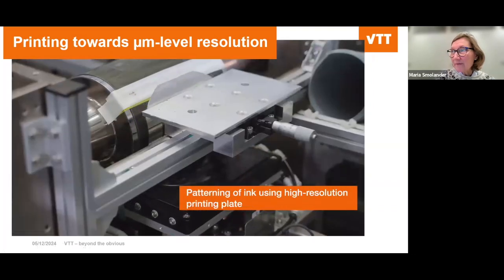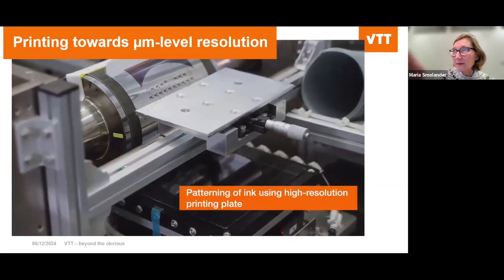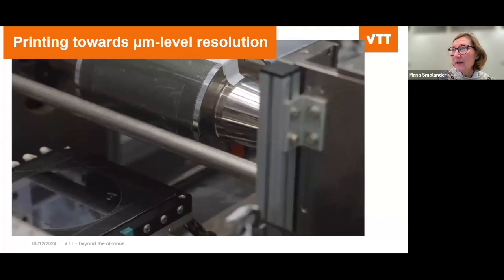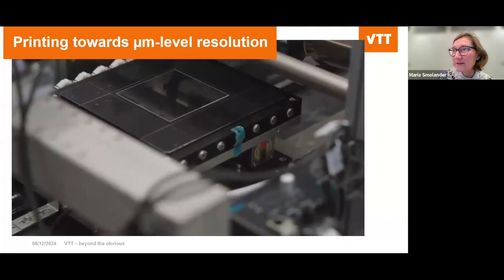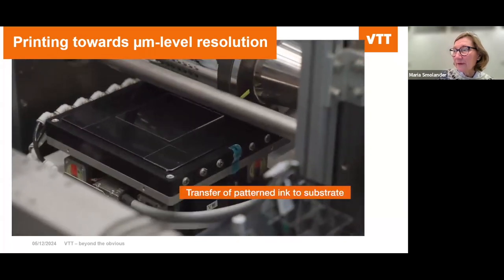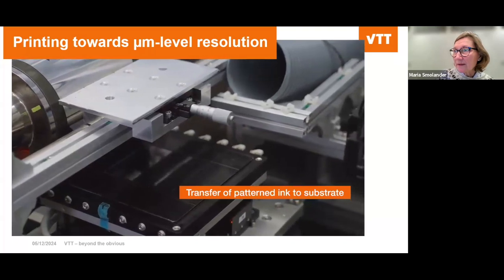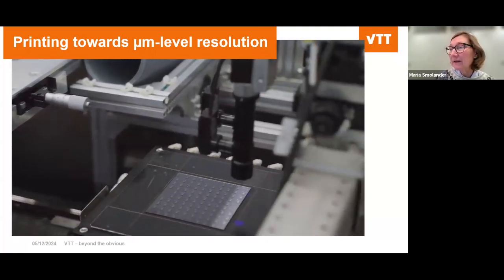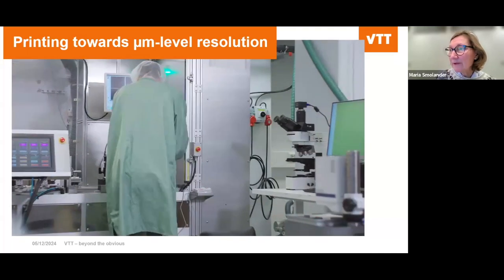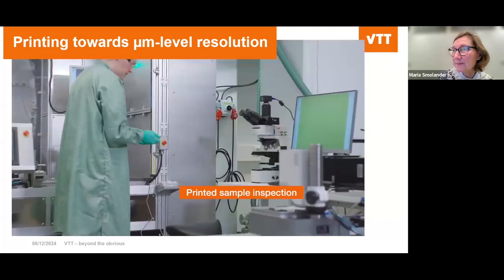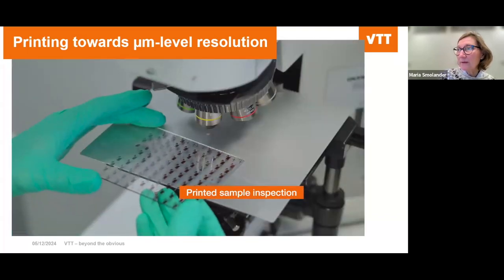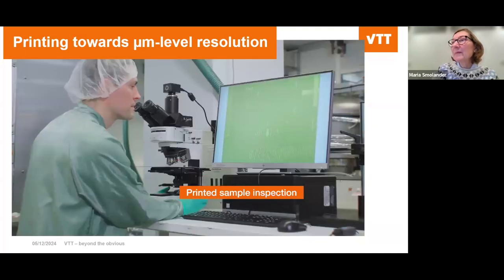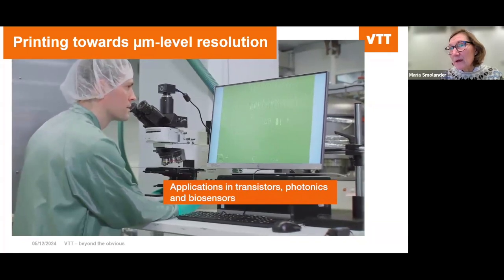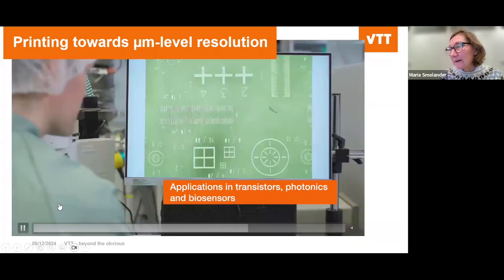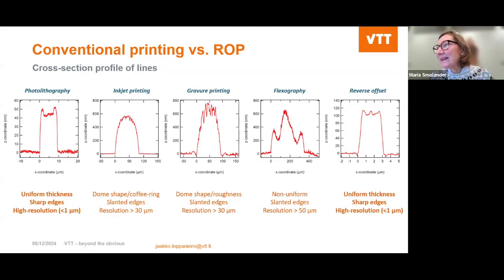And now we have the patterning of the ink on the printing plate. You can see the pattern is appearing, and okay, now the plate is removed and the substrate comes instead. And now the ink is transferred to the substrate. In this case, it is glass, but it can be anything smooth. And then here we have the devices, and it's then taken to the inspection. And indeed, the lines are about one micron line width and alignment about 2 microns, and can be indeed applied in different applications in the devices. And indeed, as mentioned, this is very unique printing method.